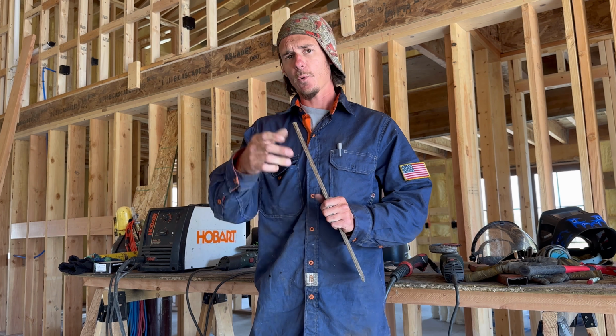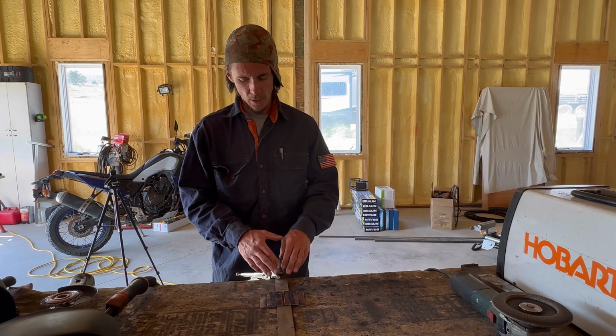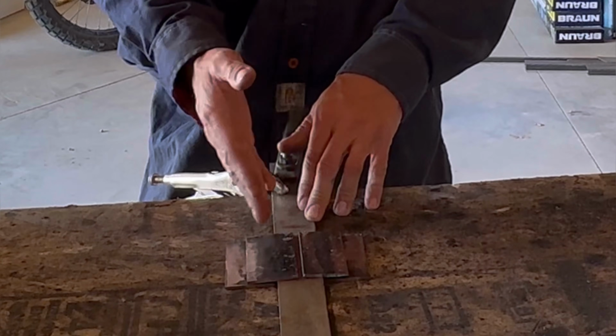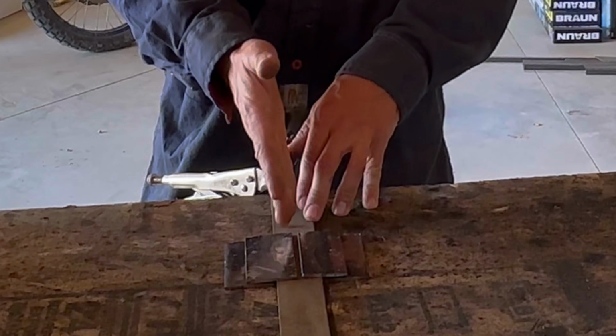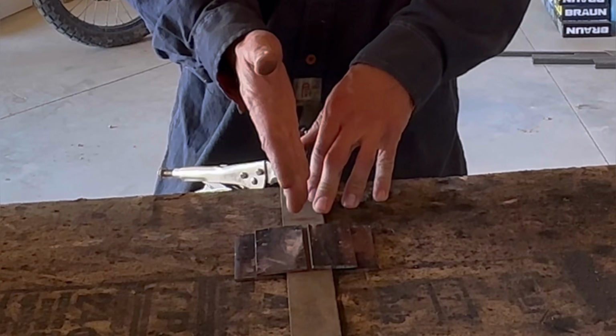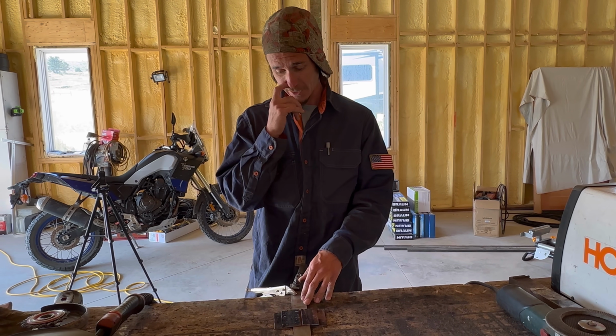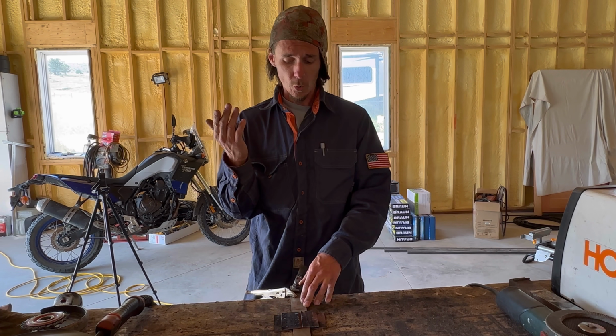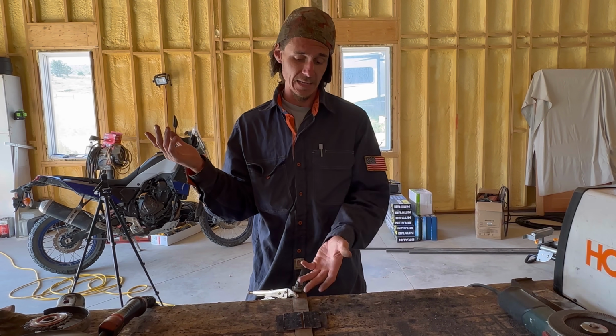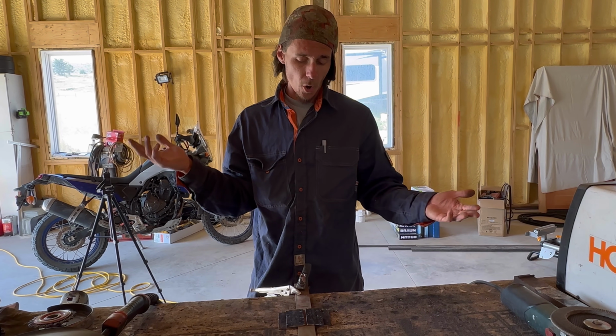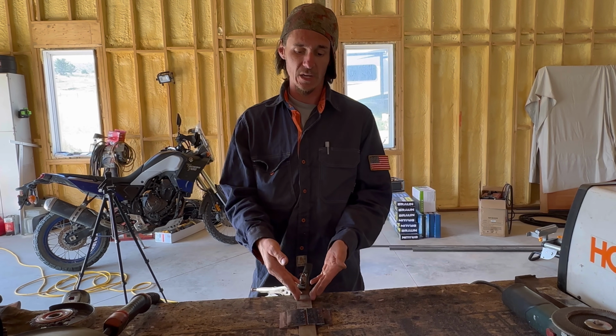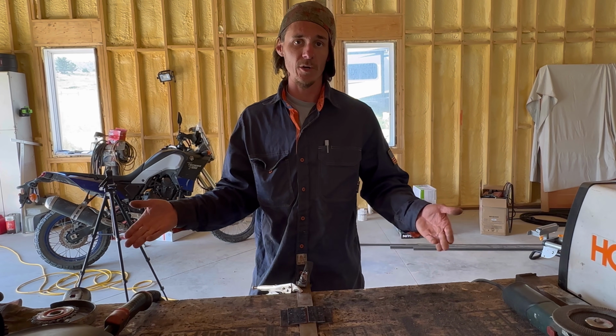So that's what we're going to do now. I'm going to go ahead and weld this fitment up here. You see it's a pretty decent sized gap, but this isn't uncommon, especially in the welding repair realm. I run into gaps like this all the time, because either bad fitment by me or just that's what's required because I had to gouge that much material out. So often, if I can fit it, I will stick a copper backing bar in there just because it makes it quicker and easier for me.